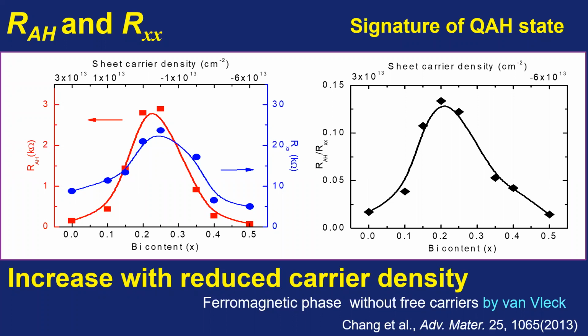And if we plot the ratio between the anomalous Hall resistance and longitudinal resistance, which we usually also call the anomalous Hall angle, as a function of bismuth content, we can see this also shows a peak in the insulating regime. In the very high electron-doped and P-doped, hole-doped regime, the Hall angle is 0.01, similar to conventional magnetic material. And in the insulating regime, the Hall angle is almost 0.15. So it tells us when you make the sample insulating, when you tune the chemical potential approaching the magnetic exchange gap, the Hall resistance indeed becomes bigger.